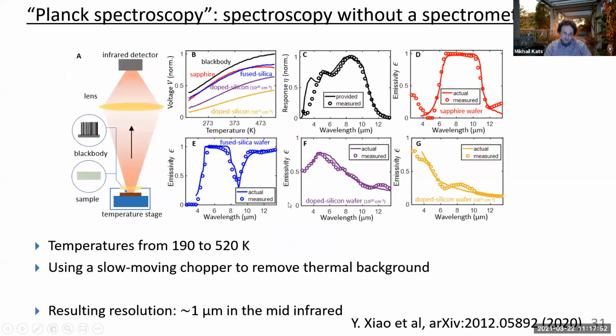So here is the experimental setup that we used. So this is a sample, again sitting on top of a temperature stage, the same temperature stage that I was showing you before. The temperatures that we're using here to do the measurement are 190 Kelvin to 520 Kelvin. So it's a pretty nice and broad range of temperatures. And we put the sample down on the heat stage over here, and we have a window so we can purge it, because if you want to go way below room temperature, you don't want condensation. So we just purge it with dry nitrogen.